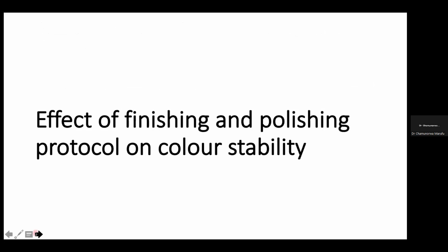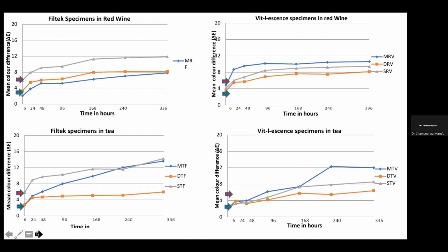And then on the second specific objective, as in the effect of finishing and polishing protocol on color stability. So in this case now we have 3 lines, and these arrows still indicate the same scenarios as in the acceptability tolerance and the perceptibility tolerance. So we were testing 3 materials, which is the Soflex disc, the mylar finish, and the stone. And in these graphs, the stone is indicated by the gray line, and then the Soflex disc by the orange line, and then the mylar finish by the blue line. So it's slightly different from the previous graph, because now we are actually comparing the 3 different polishing protocols.